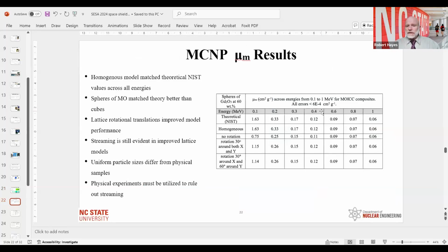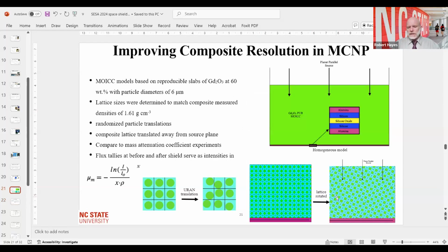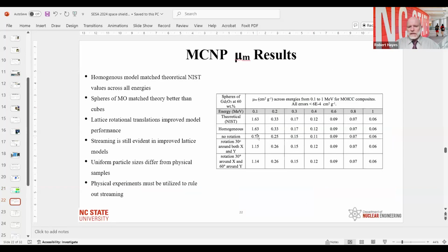So you can see up here at these higher energies, half an MeV up to one MeV, there really isn't any difference between all of the different models. But if you get down to these lower energies, say 100 keV, you can see if I'm doing rotation or non-rotation, right? That was one of the things we had, rotation and non-rotation. If I go between rotation and non-rotation, there's a big difference. If I use the homogeneous values, which we used in the beginning, that agrees with the theoretical NIST values perfectly. But if I do a 30 degree around X and Y, and I start turning these in different directions, I start to approach the NIST values, but I still never get there. And it's not until I get up to these higher energies that it doesn't make a difference anymore.